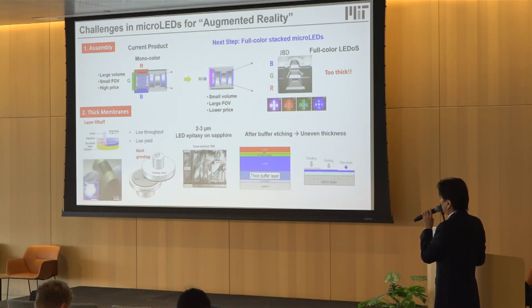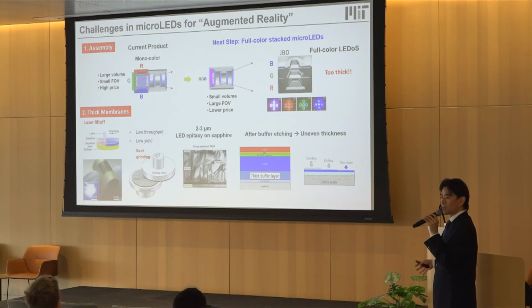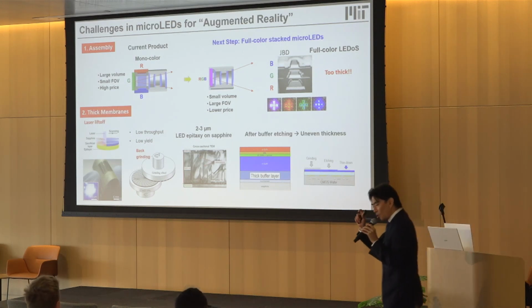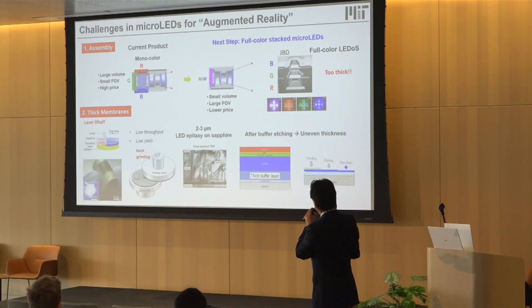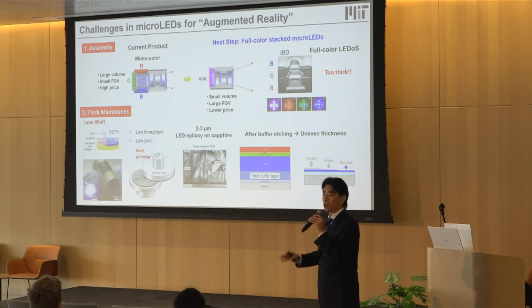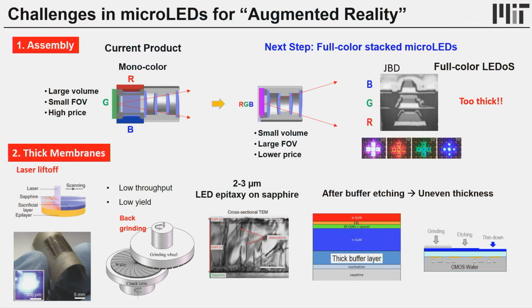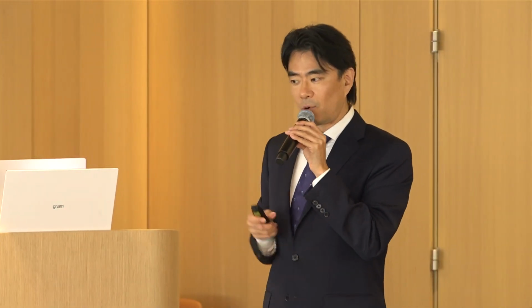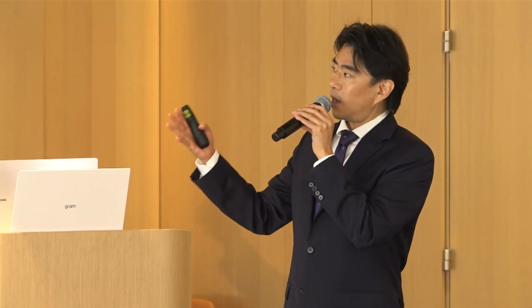Okay, so you may say, after releasing this LED, why don't you do dry etching to make it thinner? Yeah, that's possible, but in order to have precise optics there, this uneven surface is unacceptable. By doing dry etching, you cannot have a precise stop at a certain interface, so the thickness of the layer is not uniform. That is problematic. So far I gave you two different challenges.